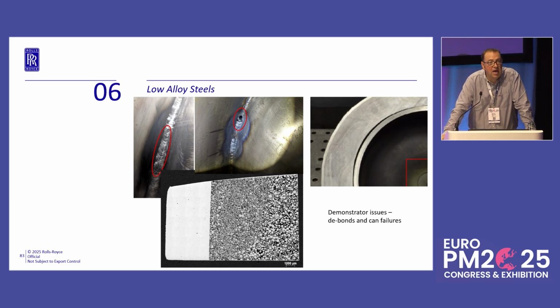So one of the problems we had was that the can leaked. And we had the atmosphere from the argon HIP vessel, unfortunately, go in. So what you can see in that bottom image is the can material. It's relatively thick. And then you can see lots of lovely A508 powder that unfortunately hasn't consolidated together. So we managed to track down where the leak was, and you can see there it's a hole in the weld. We also got quite an interesting problem with the internal can, where it actually debonded during the cool down cycle because of the CTE mismatch.